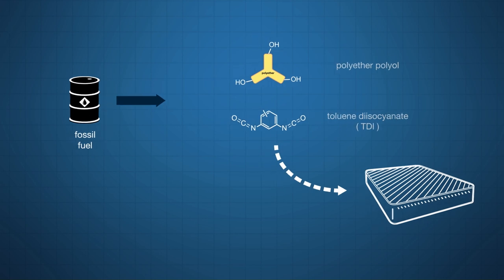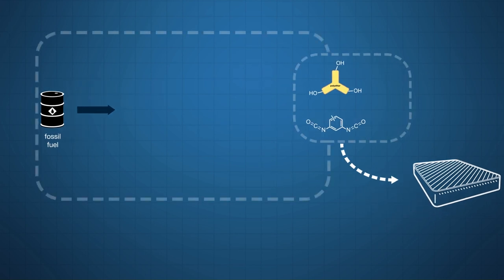The synthesis of toluene diisocyanate starts by the catalytic reforming of heptane from oil to toluene, which will undergo nitration to nitrotoluene and is subsequently reduced to toluene diamines.